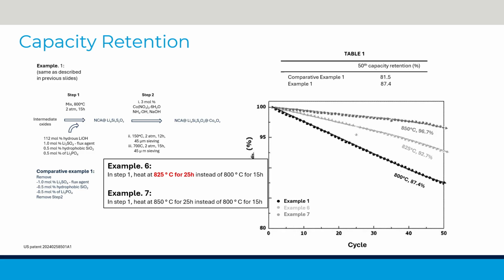Example number 6, with 825-degree heating, exhibits a capacity retention of 92.7%. Further increasing the temperature by 25 degrees to 850 degrees shows significantly improved capacity retention to 96.7%. So why does this matter?